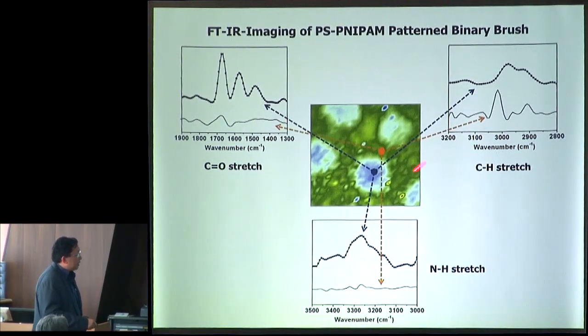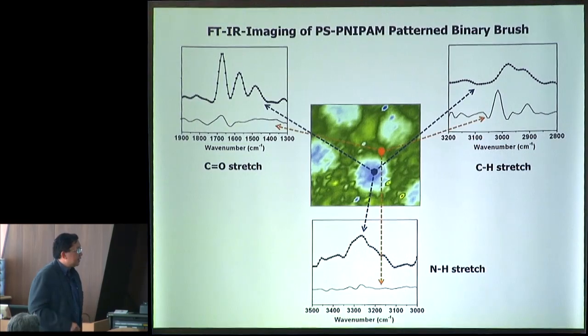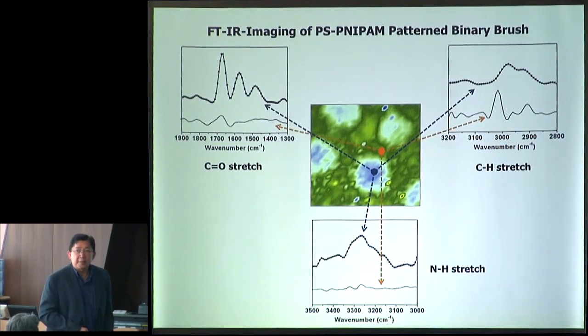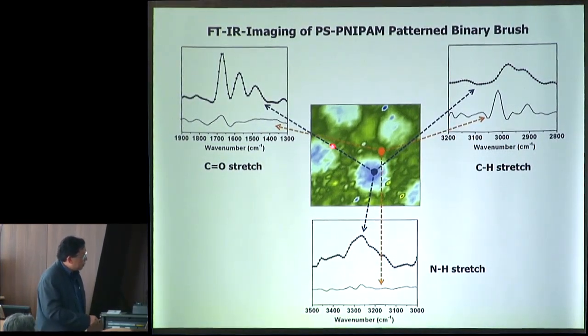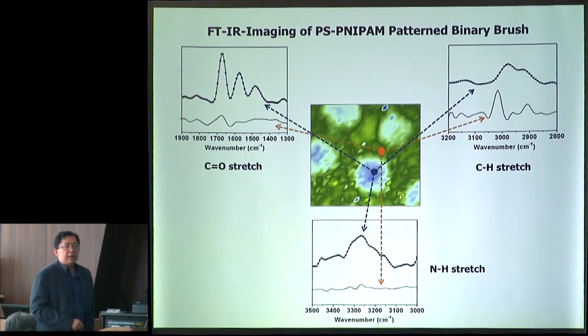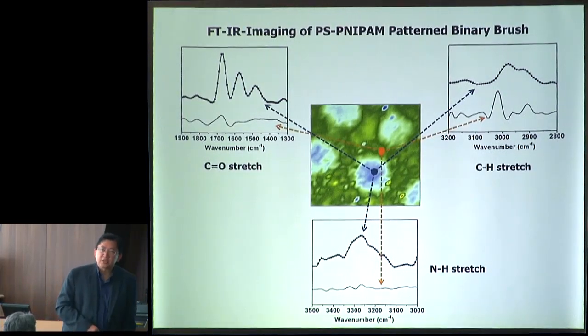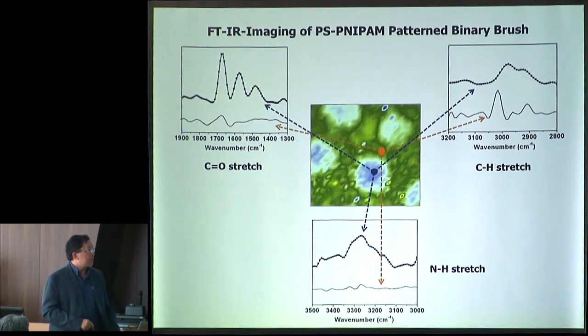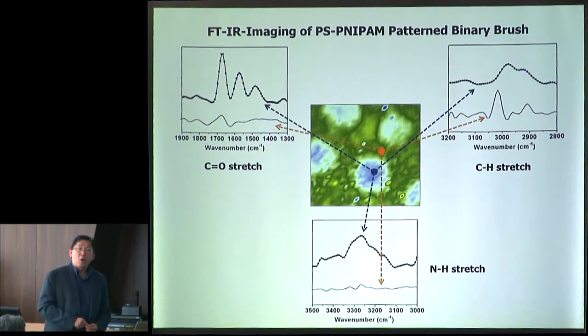So for example, the green region here represents that of polystyrene. No carbonyl stretch, no NH stretch, but a nice CH stretch around 3000. On the other hand, we know that the blue or greenish blue is poly-NiPAM because we have a nice carbonyl stretch, a nice NH stretch, but a lower CH stretch for the polymer NiPAM backbone.